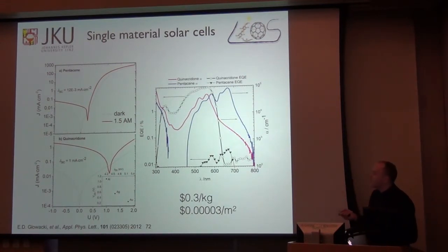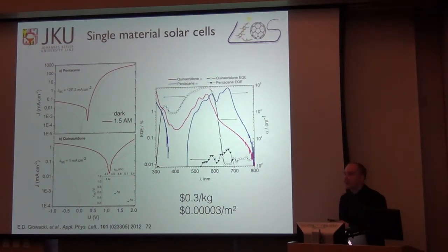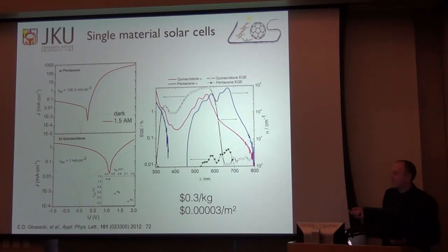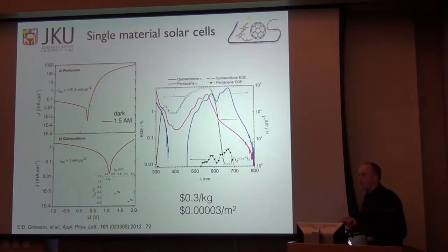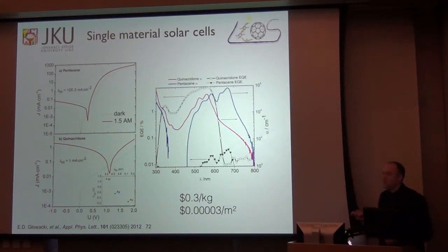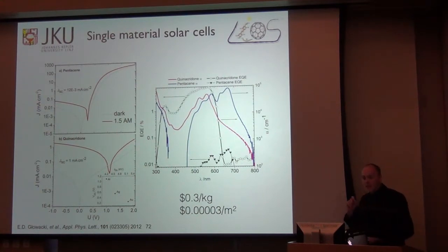If you put pentacene between an ITO-PEDOT electrode and an aluminum back contact, just like in about every other organic semiconductor, you get about 10 microamps per centimeter squared of photocurrent. But if you put quinacridone in, you get over a milliamp. So you have 15 or 16% external quantum efficiency from just quinacridone by itself. The same phenomenon that's causing this crystal-induced color change is causing a delocalization of the excitations, which means we can easily, if not freely, excite photocarriers without a heterojunction.